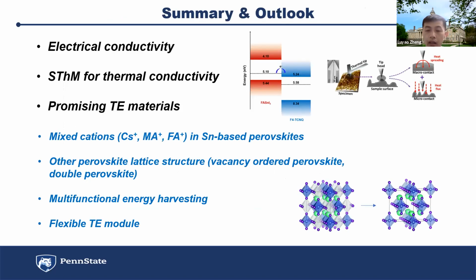And finally is a summary and outlook. So in this work, we try to improve the electric conductivity by small molecule doping, as shown here. We use this F4-TCNQ to induce p-type doping into the perovskite and give us increased electric conductivity. And also we try to set up a new method system to measure the thermal conductivity of thin films based on this SThM method. And we can obtain a pretty good ZT value from this material at room temperature.